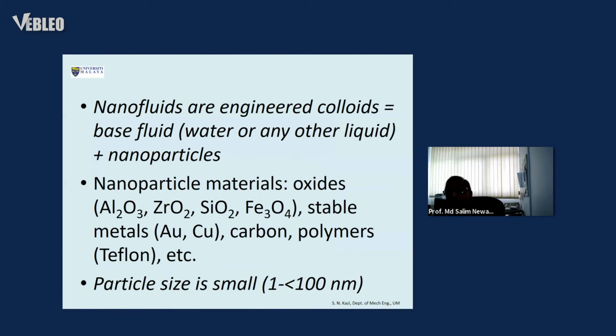So we find that not only natural polymeric additives, but also nanoparticles have been used for 20 years, a long time ago, for heat exchanger performance enhancement, by adding them to the heat exchanging liquid to try to enhance the performance of the heat exchanger. The same research is being done at the University of Malaya, and the same liquid and the same particles can be used for fouling mitigation.